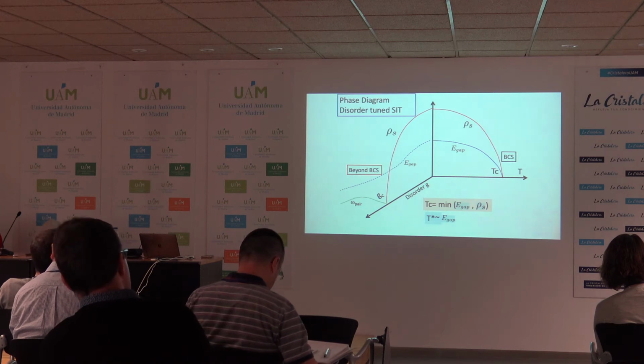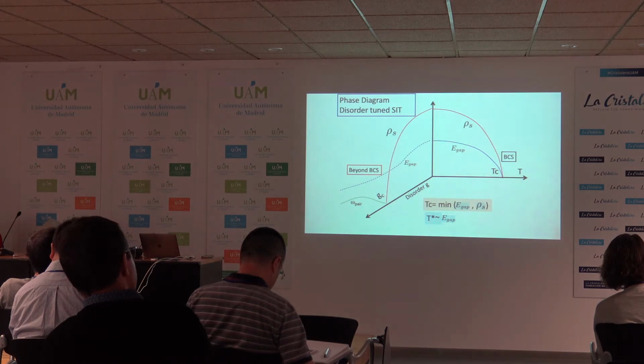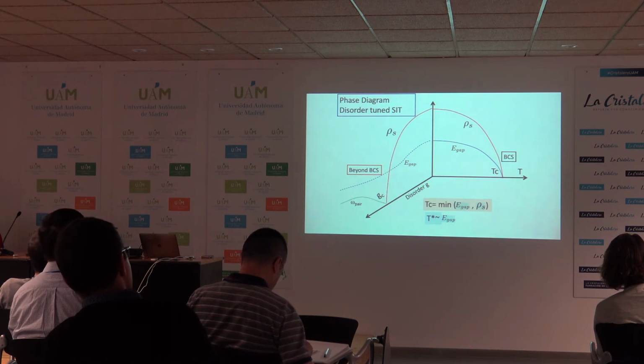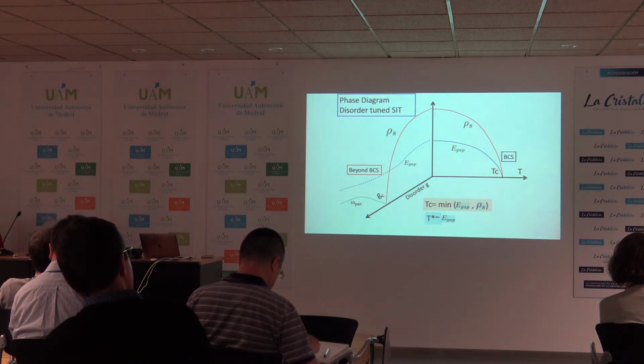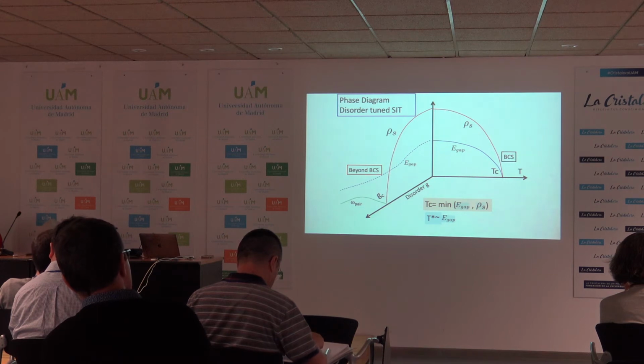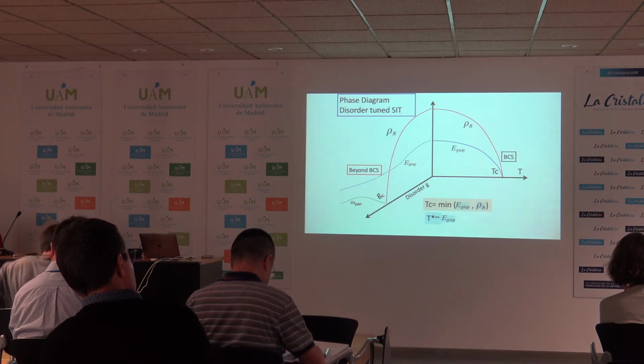So here's another sketch which summarizes the phase diagram. And then again, I'll give you the details of the calculations from which such a phase diagram is derived. Okay, so let's look at the two energy scales, the single particle gap and the superfluid density, or the superfluid stiffness. Both vanish at Tc. This is a standard BCS superconductor with no disorder. And now I add this axis, which is disorder, and you should think of it as just random inhomogeneities on some very short length scale, atomic scale.